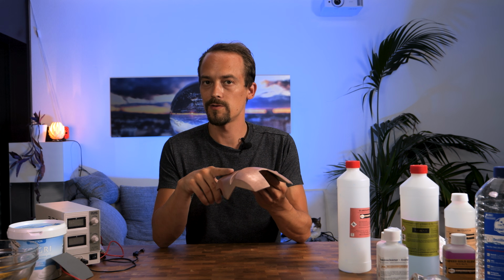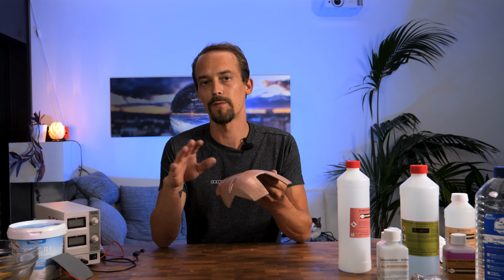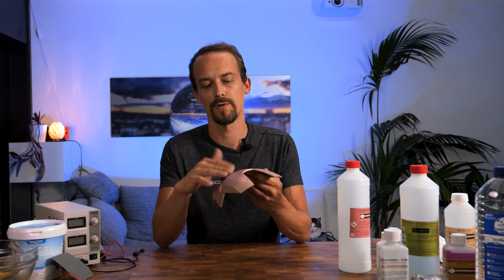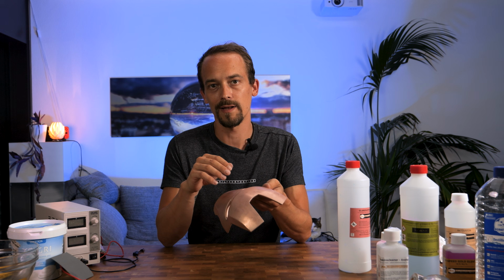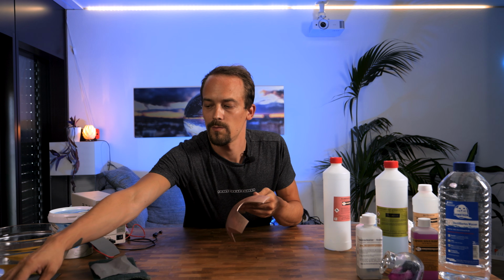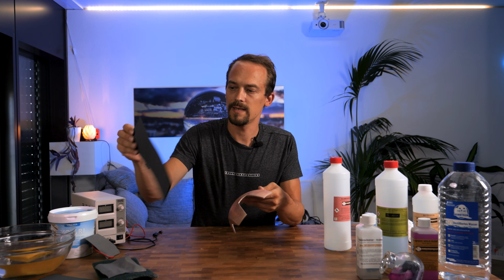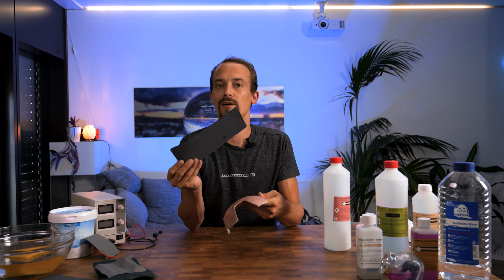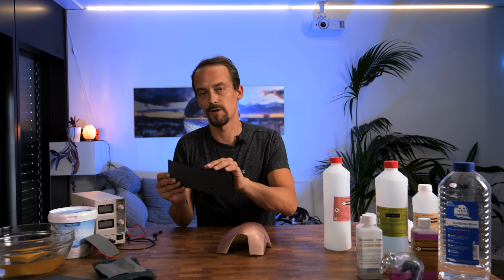So what I'm now going to do, after I added a thick layer of copper, I will grind it down again to smoothen it out, to get rid of all the bumps. Because as we learned earlier, your plating is always going to follow all your surface imperfection. It attaches everywhere in the perfect same amount of thickness. So now that we build up enough, we can grind down all the high parts to match the low parts and get a nice, even, smooth finish. We will start out with a 2000 grit sandpaper, but this time we're starting out dry, not wet, because we want to actually remove material.